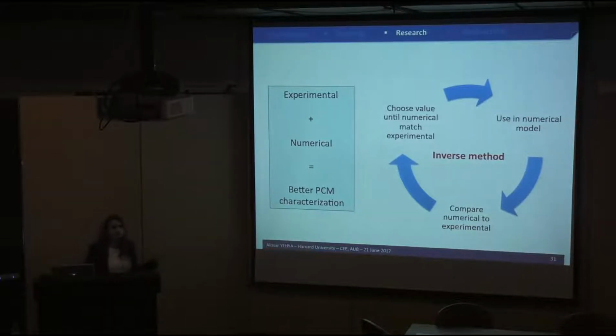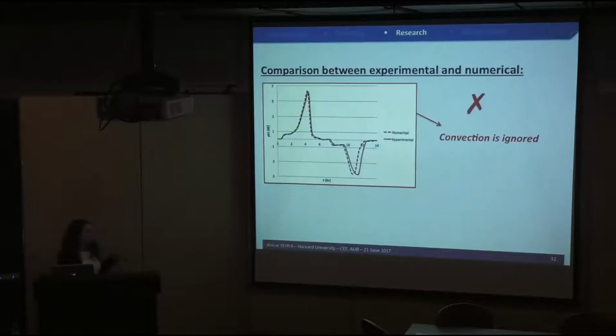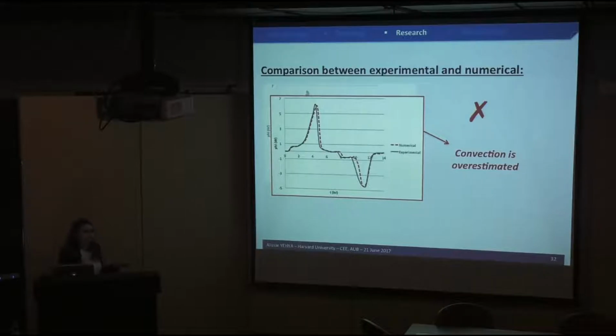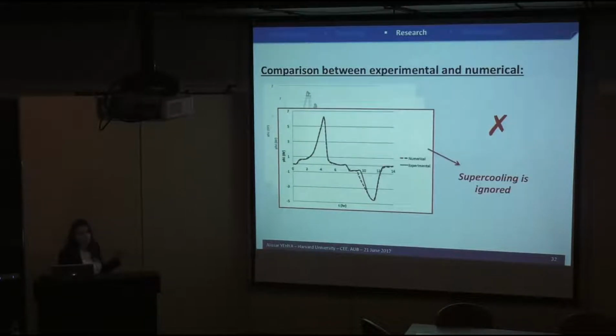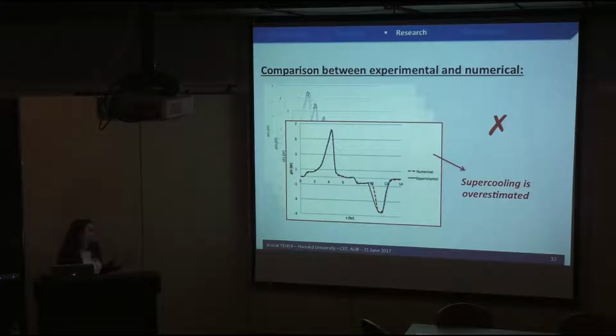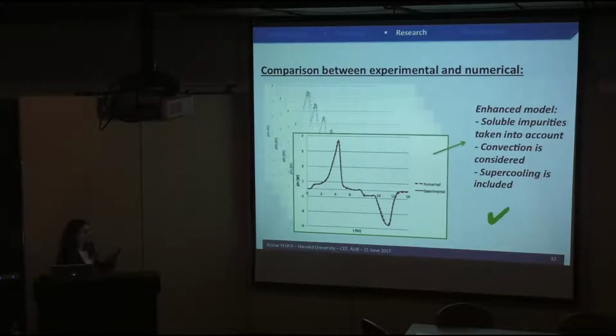And we solved it inversely. So for example, for the supercooling, we don't know the supercooling degree. So we put in a supercooling degree, and then we model, and then we try to fit our model to the experimental results and infer inversely what the degree of supercooling is. So for example, this is a comparison between the numerical and experimental approach. Here's the numerical in red, the experimental in blue. If the convection is ignored, we won't have this fitting. If it's overestimated, because we also don't know the degree of convection here, it doesn't fit. So we use some fitting methods. Supercooling, if it's ignored, we can't predict accurately the onset of solidification, and if it's overestimated, we don't predict it accurately either. So we use a fitting method and decrease the errors in order to have the experimental curves coincide with the numerical curves.